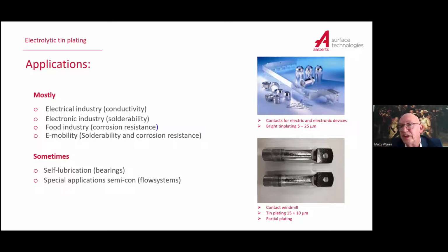In the electric and electronic industries, you have to solder on some parts. You can do that very easily. Mostly those parts are made from copper. You put tin on them, and tin is less noble than copper. That means it protects the copper from oxidizing. So in that case, it's also a good corrosion resistant coating. Sometimes you use it for self-lubrication and special applications in the semicon. It's used for flow systems. And what you see here for the contacts, it's just a general